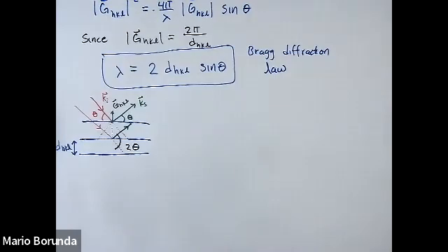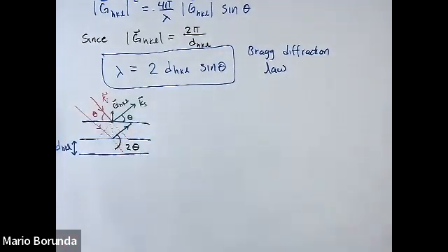That improves your resolution. Then you have this powder, which you pulverize by putting the material in a mortar and pestle. You have this fine, pulverized powder, and then you could rotate the material through an axis, or in this case, you can rotate the detector through an axis. And that's what you're getting. Because you have a bunch of little crystallites in the powder, you get a bunch of diffraction at particular angles.